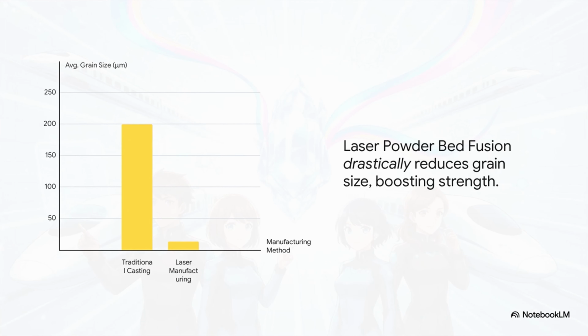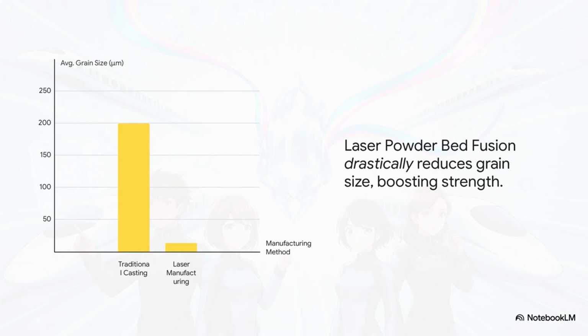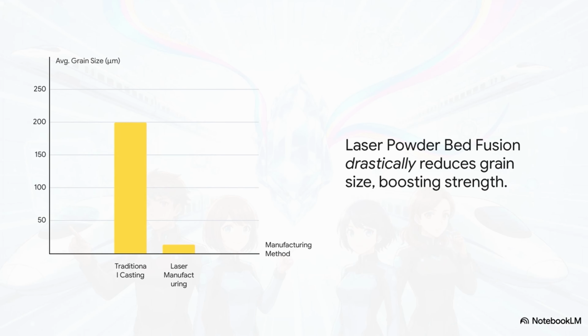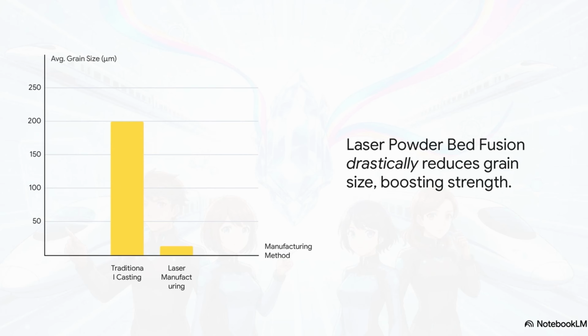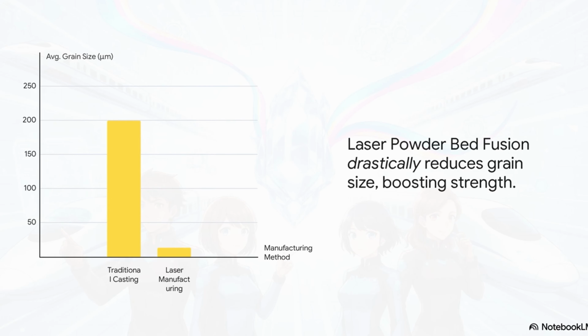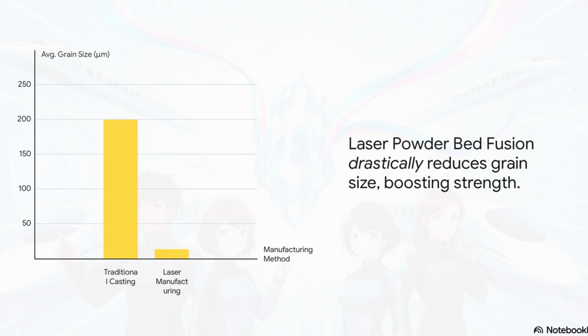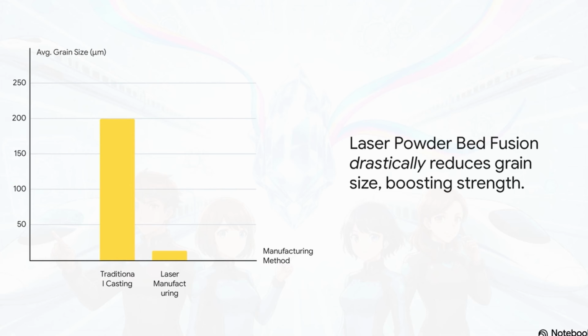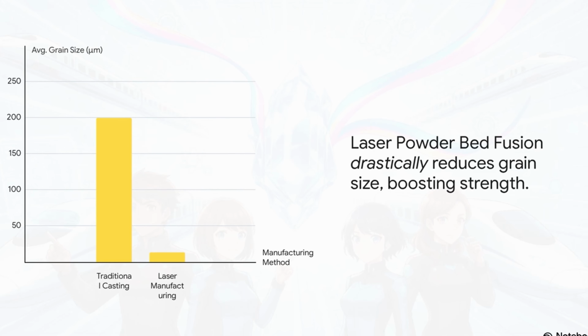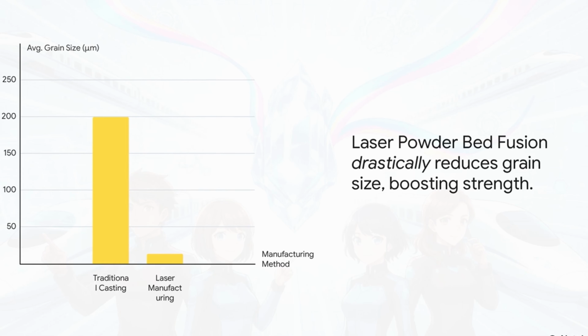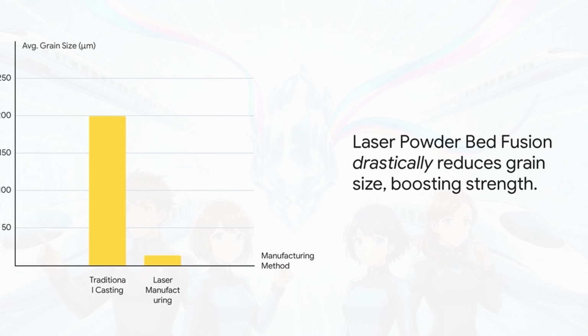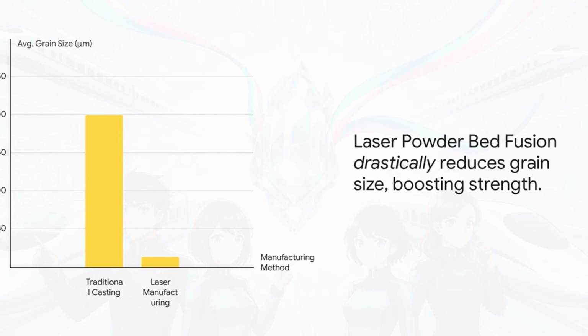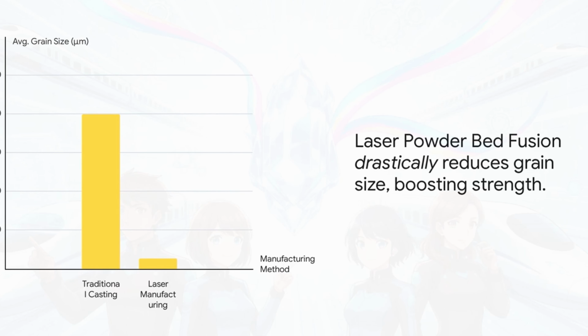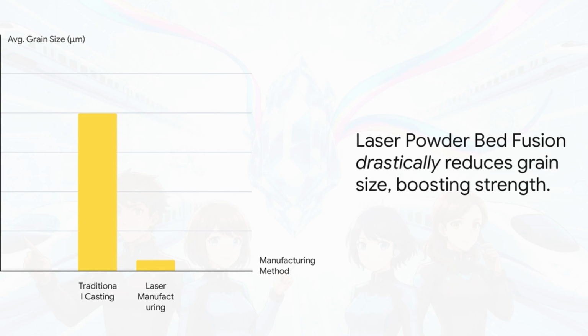The solution? Lasers. Of course, it's lasers. They use a process called laser powder bed fusion, which is a lot like 3D printing with metal. High-powered lasers flash melt and fuse tiny bits of alloy powder, layer by layer. It happens so fast that the atoms are frozen in place before they have a chance to separate. And just look at the difference. The grain size plummets from a weak 200 micrometers down to a super strong 13.4.